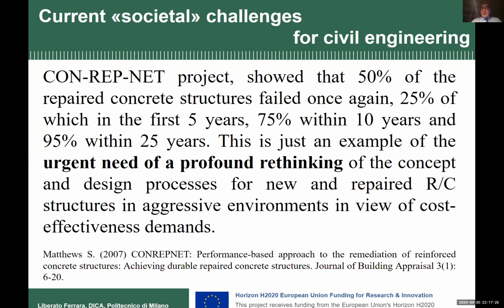According to a survey made by a European project about 10, 13 years ago, 50% of repaired concrete structures fail once again after the repair, and a quarter fail in the first 5 years after the repair. So we really need an urgent, profound rethinking of the concept and design processes for new and repaired structures in aggressive environments.